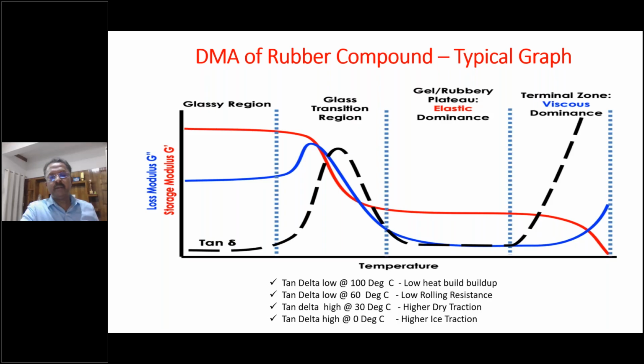This is a typical DMA graph of a rubber compound. The black one is tan delta. The rubber has 4 regions: glassy region, glass transition region, the elastic region, and the viscous region. The tire operates within the elastic region, the third region. A low tan delta at 100 degrees leads to low heat buildup. A low tan delta at 60 degrees indicates low rolling resistance. A high tan delta at 30 degrees, high traction. And again, high tan delta at 0 degrees, high traction. So tan delta is the most important parameter for tire performance evaluation with regard to heat buildup, mileage, rolling resistance, traction. It is a very important parameter for rubber compound analysis for tire rubber application.